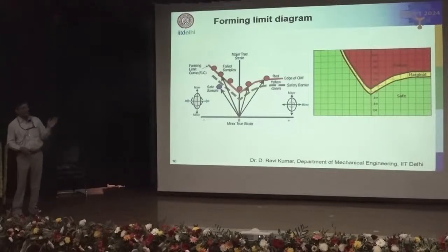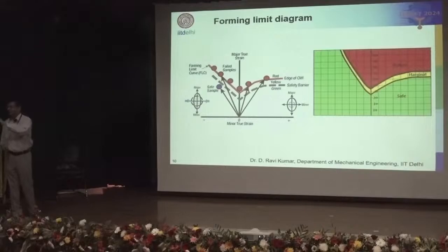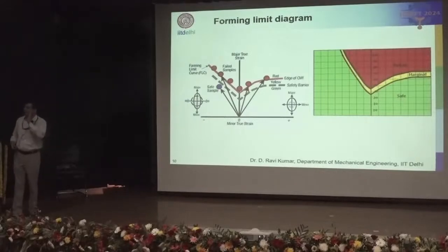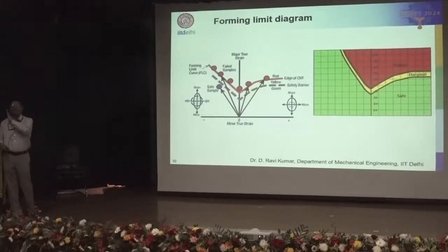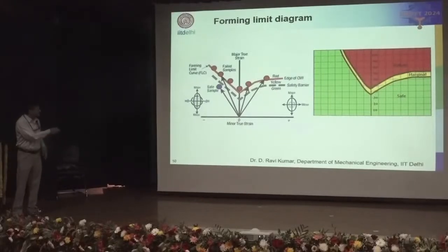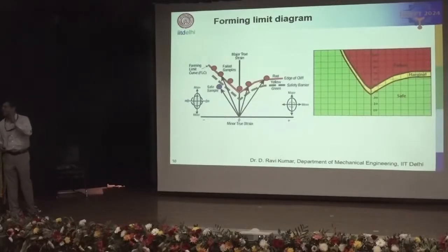Often, even though we call it a curve, it is plotted as a band consisting of an upper limit and a lower limit. So if the strains fall above the curve, it means that the material is definitely going to fail. And if the strains measured on the surface are below the lower limit, it is definitely going to be a safe operation. But if the strains are within these two curves, it means that the material is likely to fail. So that's the critical region.